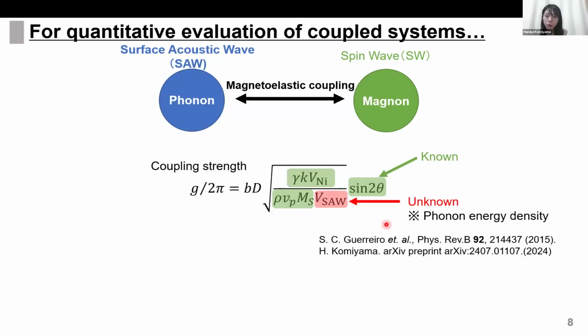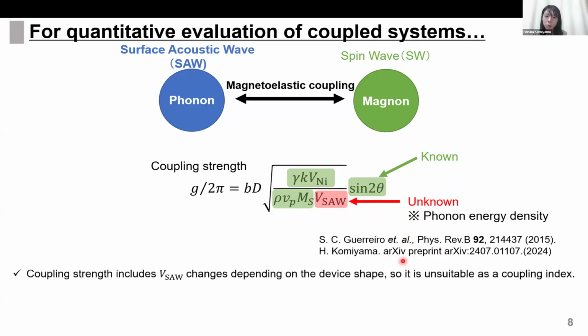And then the surface acoustic wave mode volume, VSAW. The fact that VSAW exists in the denominator of G indicates that the energy density of phonons increases as the mode volume decreases, leading to increased interaction with magnons. The VSAW can easily change depending on the device geometry or material. Coupling strength G, which includes VSAW, is unsuitable as an indicator for quantitatively expressing the coupling system.